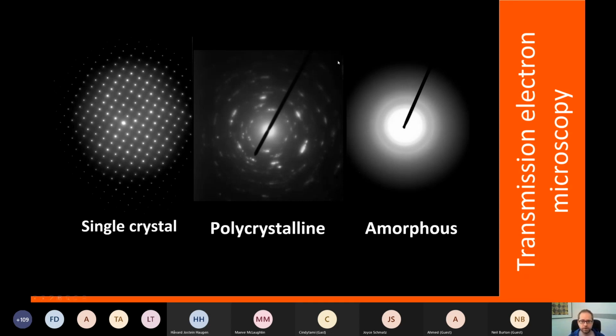We can also look at polycrystals, then we get ring patterns here. And we can look at orientations, for example, common orientations of many particles together, or simply analyze what these particles are using diffraction. Or we can get amorphous diffuse patterns, as you see in this case here, to say something about the degree of amorphization, or simply whether there is amorphous material inside our sample.